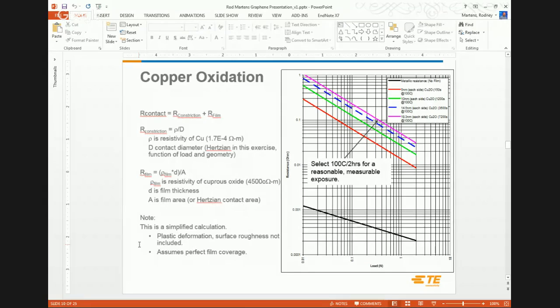So I'll walk through this little exercise right here, which is more fundamental contact physics. Anytime we bring two surfaces together, it's a function of the constriction resistance, which is dominated by the geometry and the resistivity of the material, and the film resistance. So do we have an insulating film on top of it? For a clean contact, we would neglect the second term. The constriction resistance is essentially the resistivity of the base material divided by the diameter of the area in contact. So we know the resistivity of copper, and we'll estimate the contact diameter by just calculating the Hertzian diameter. That's fairly straightforward, and that would be indicated by the black line over here on the curve.